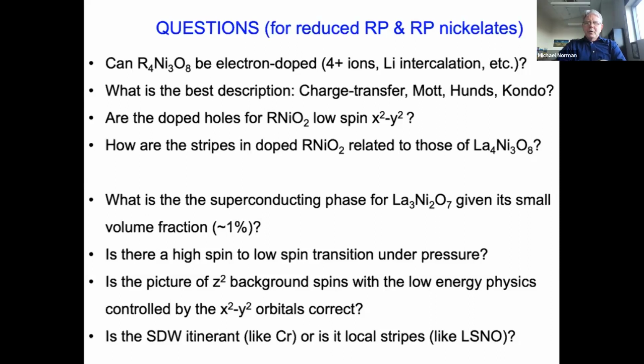So for the new materials, which are Ruddlesden-Popper, I think one of the interesting questions is, what is the superconducting phase? It's been recently shown, and I think this will be presented here at the meeting, that people have been able to do Meissner effect now, and it appears that the superconducting volume fraction is only about 1%. That indicates to me that we probably don't know what the actual superconducting phase is under pressure. Do you indeed have a high spin to low spin transition under pressure, and therefore is superconductivity associated with low spin physics like in cuprates?